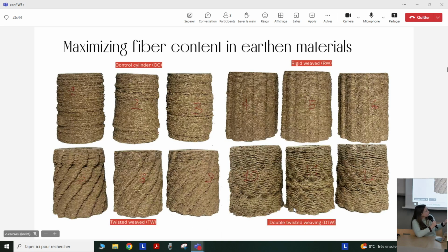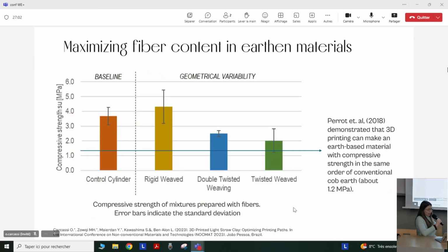But then we said it's not just about the materials. We're using a technology that can really help us play with different geometries. So we tested different cross-sections, really to understand if we could also improve the mechanical properties of these elements. And what we realized is that, of course, the geometry plays an incredible role. So this is, of course, according to the load direction. If you have a vertical load, the best cross-section is where you have more rigid walls in that direction.